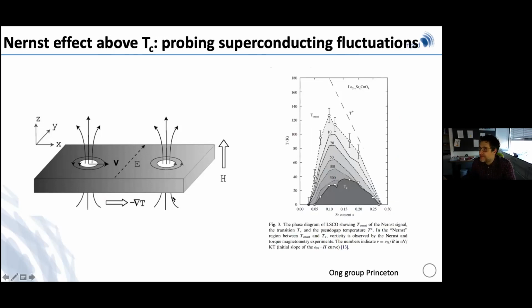And there have been famously very interesting experiments done by Ong's group at Princeton, who showed that in the cuprates you have a very large Nernst effect in very important regions of the phase diagram of the cuprates. Although this is a highly controversial and discussed topic, it has been taken as indicative of the presence of pre-existing superconducting fluctuations above TC.